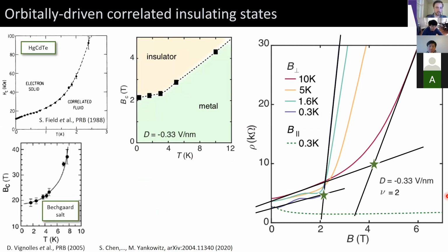Now, these types of phase diagrams have actually been observed before in a number of different correlated systems. So for example, in Bechgaard salts, under pressure, a similar phase diagram was observed between a metallic and a field-assisted insulating state. And this was thought to be driven by a spin density wave. And in mercury cadmium telluride quantum wells with low density, Wigner crystal formation was thought to drive some sort of phase boundary between a correlated fluid and an insulating electron solid.